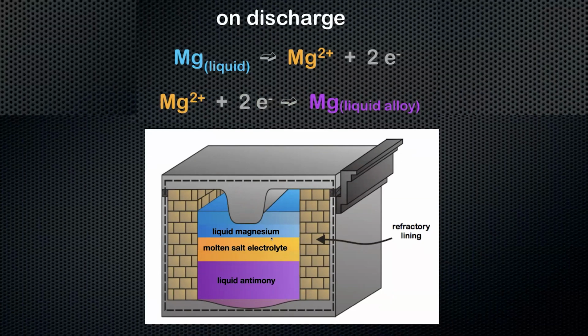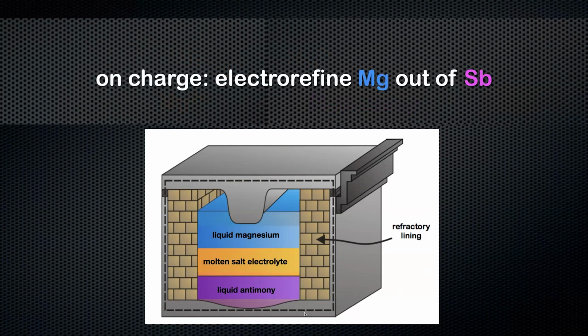And on discharge, magnesium wants to alloy with antimony, but I just told you magnesium is insoluble in the electrolyte, so magnesium can't get to the antimony. But if magnesium becomes magnesium ion by getting rid of 2 electrons, magnesium ion can go through the electrolyte. And when it gets to the other side, it acquires 2 electrons. And those electrons that are generated at magnesium and are donated at antimony go through the external circuit. And as they go through the external circuit, they power the devices. And then to charge the battery, we force current through, just as I showed you in the liquid metal battery. We force current from the antimony to the magnesium, and then that causes the magnesium to be refined out of the antimony. So it purifies the antimony, purifies the molten salt electrolyte,